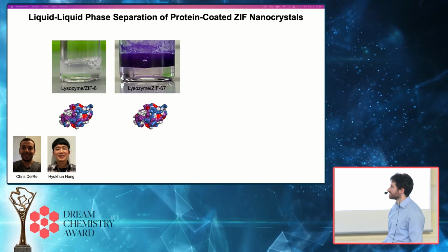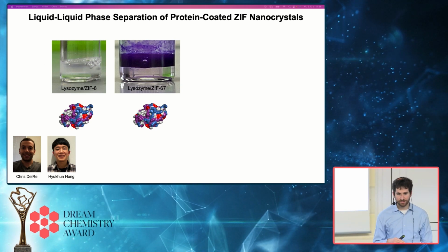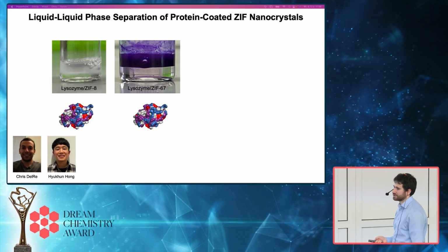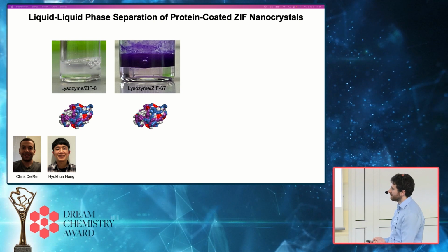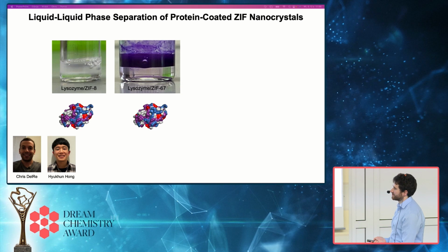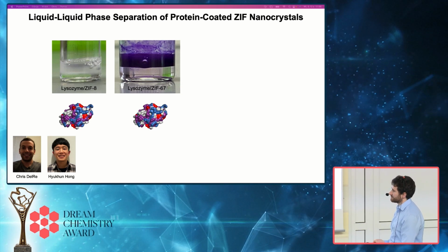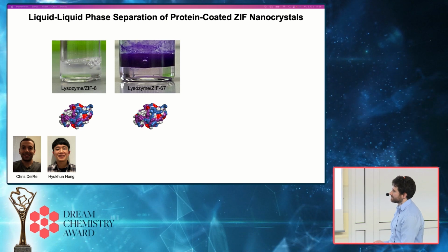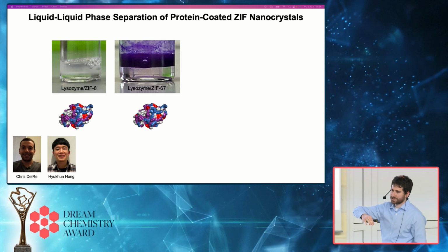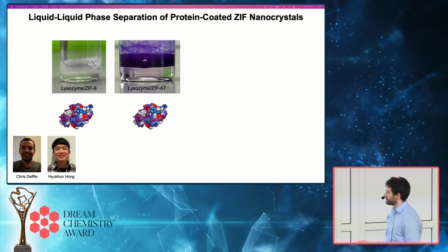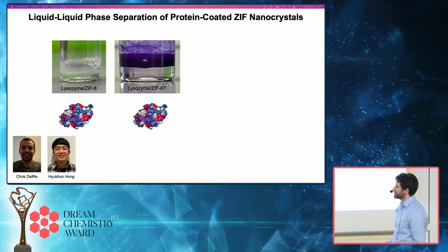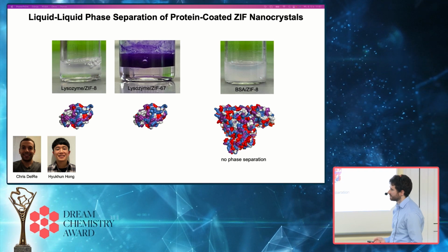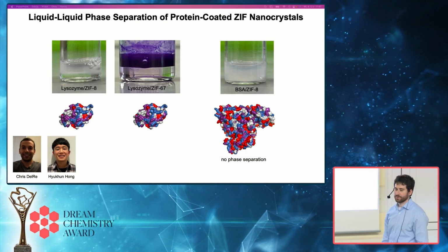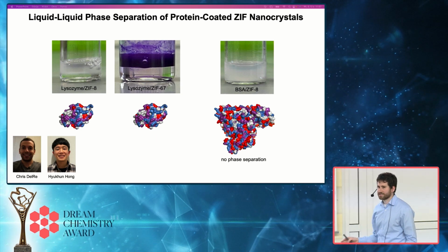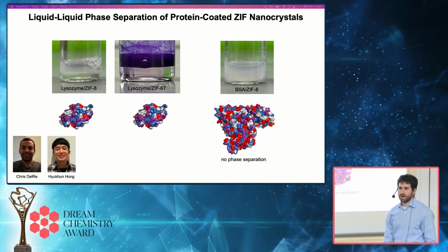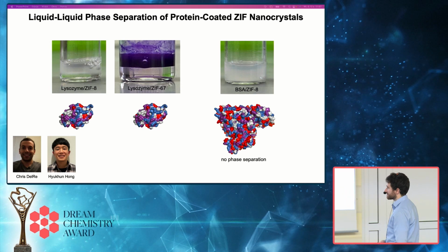We also see some really interesting phase behavior depending on the size of the particles we're working with and the concentration of the particles, where in some cases with certain proteins, we see what looks like a liquid-liquid phase separation over time, where we see a liquid region that contains a high concentration of our MOF particles and protein, and one that contains a very low concentration of MOF particles and protein. These MOF particles are less dense than water, so the particles actually rise to the top. If you put alcohol in the solution, then they'll sink back to the bottom. But we see this phase separation behavior at some concentrations and with some particle sizes for certain proteins, and we don't see it at all for other proteins, regardless of the size of the particles or the concentration. Trying to really understand what's dictating this different phase behavior is something my group is working hard to understand, and something that we're really interested in.